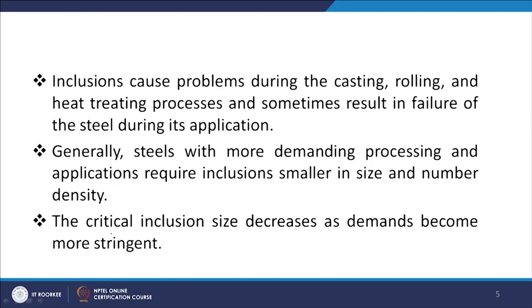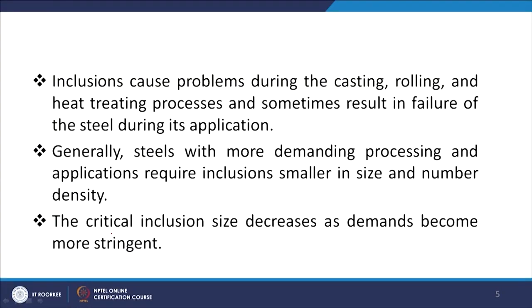Steels with more demanding processing and applications require inclusions that are smaller in size and lower in number density. For better-quality steel, both the inclusion size and the number of inclusions must be minimized. The critical inclusion size decreases as demands become more stringent, and end users specify a maximum allowable inclusion size for critical applications.